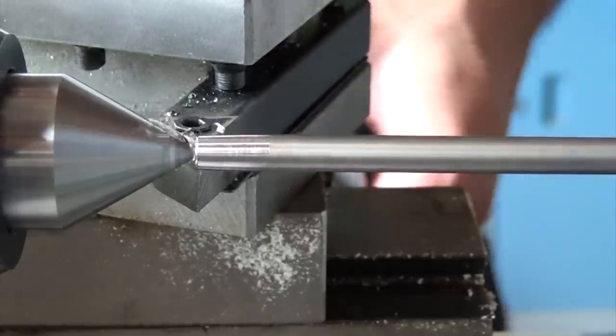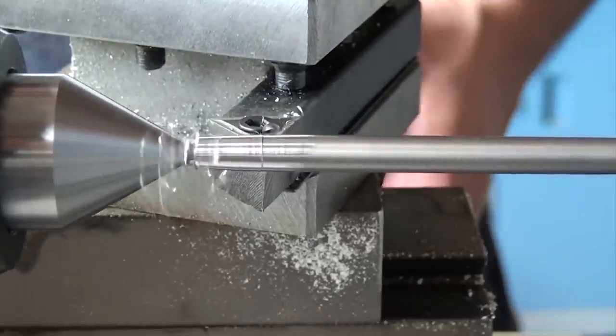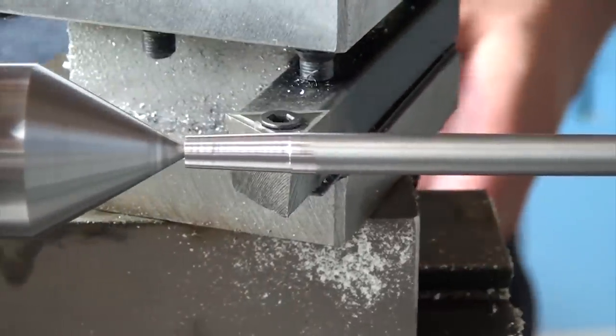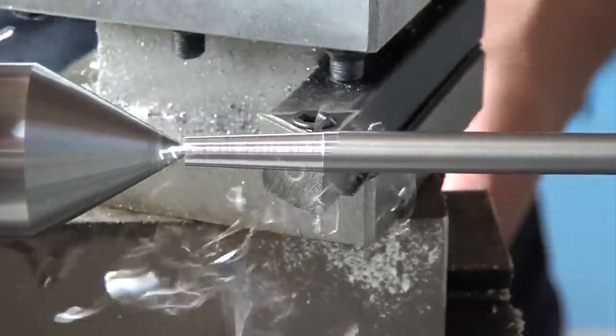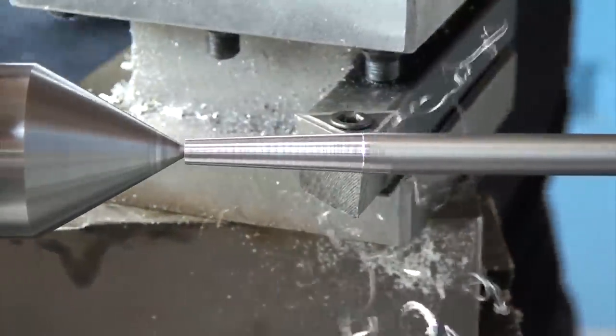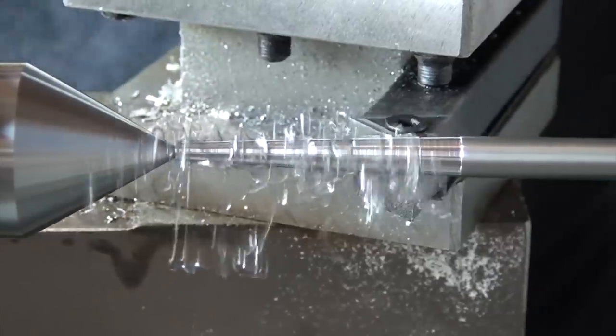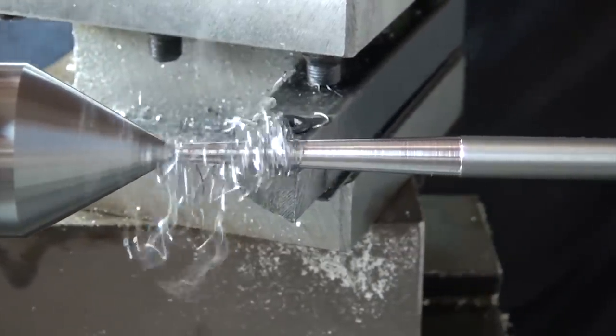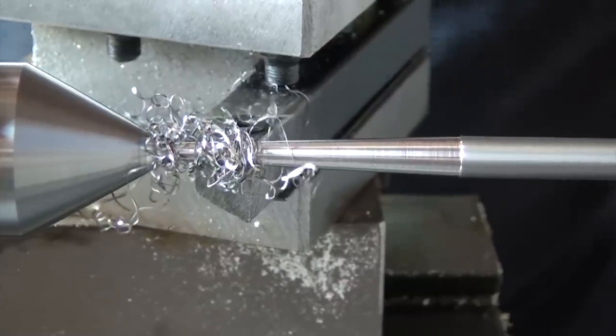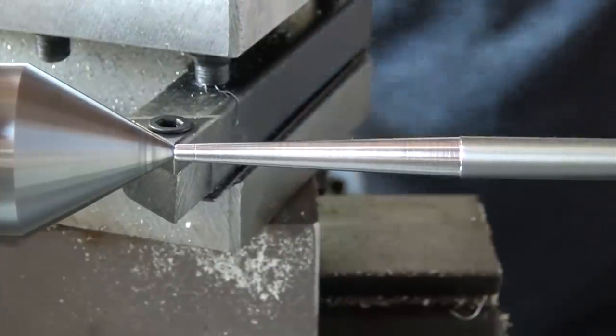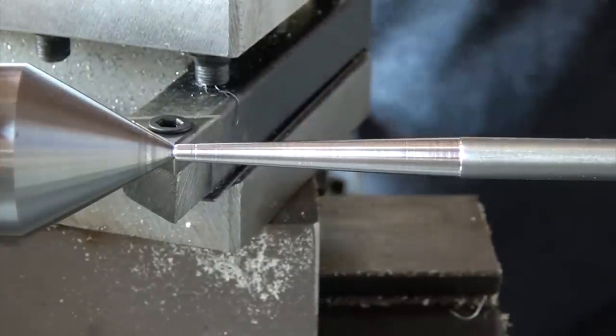Cutting titanium, especially a piece this thin and bendy, is best done slowly. I usually take no more than five thou passes, which lets you slowly develop your taper. When you're getting close to having your whole taper established, you'll want to change how you take your cuts. Normally, for the first few, I'm pretty aggressive with how quickly I'm moving the carriage back and forth to take my cuts, but that doesn't give a very good surface finish. For the last pass, you'll want to slow down how fast you're moving everything, and try and maintain as even of a speed as possible. My lathe doesn't have power feed to cut tapers, so it takes a bit of practice to do this by hand and get good results. If it's not perfect, that's okay, we'll be sanding and adding other ornamentation in a moment, but the better this is, the less work you have to do later.